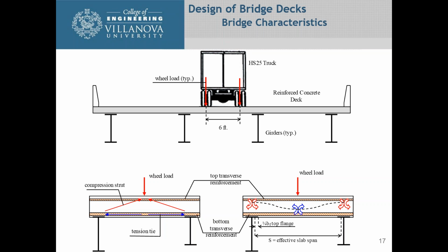And so what happens is the bottom reinforcing in the transverse direction acts as a tension tie, and you have a compressive strut that goes from the point of the wheel load to the supports, which would be the two girders. Now this is the empirical formula, and this is what is used primarily in Canada for their design. It tends to yield lower reinforcing than what you would get with what we call the traditional method, which is how we design them in the United States. And that is shown on the right. On the right is the flexural model, where you have a wheel load put at mid-span and it wants to make that deck curve, where you have a positive moment in the center and negative moments over the supports. And that's the model that we used in our design.